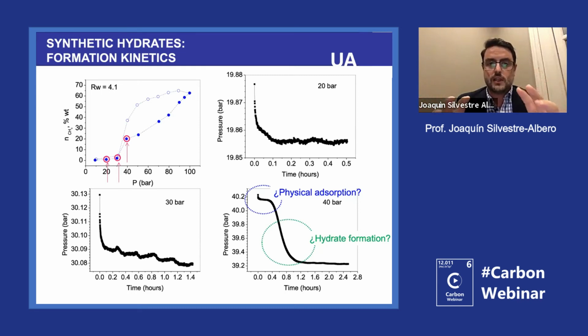So this is an indication of how fast we are obtaining this point in the isotherm. You see that in 1 hour, more or less, 1 hour and a half, everything is done. So whatever is happening there, it takes only 1 hour, while, as I say, in the natural environment, you need weeks to make these bulk hydrates.